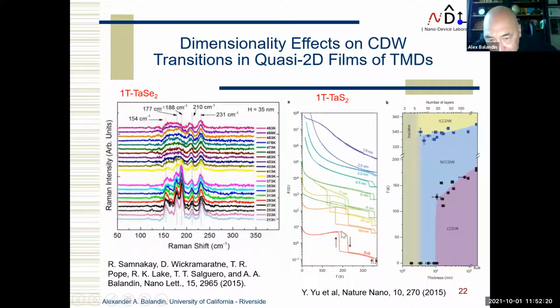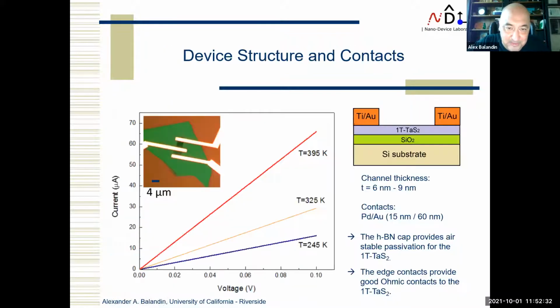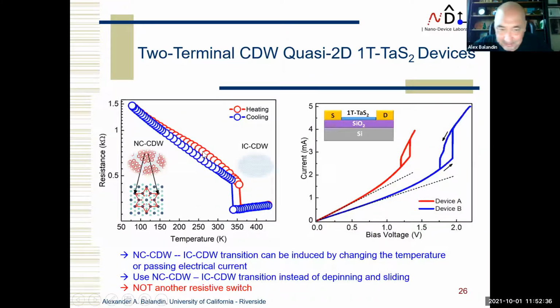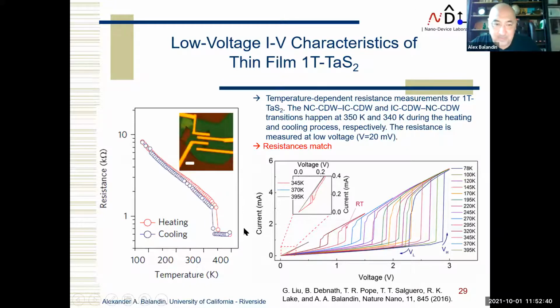As you can see, it starts from bulk and goes to small dimensions. At the order of 9 nanometers, this hysteresis disappears, while the other one still persists. You can see what we also did here. In this one device, the hysteresis disappears, but the transition at room temperature is robust. So our results are in line with this. To summarize, I'm curious to play with effects which can be seen above room temperature, and it's interesting to have a quantum material and quantum device at room temperature. From the other side, this big hysteresis also disappears when the device thickness becomes smaller than 9 nanometers.